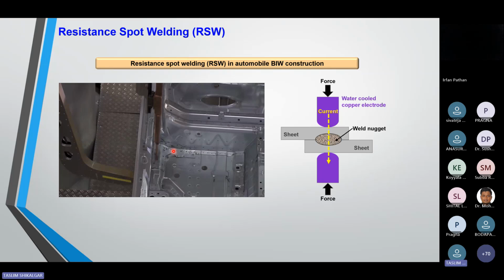connecting two sheets with the help of the resistance spot welding, and they are applying some force and passing some current. Now with the help of current they are generating this resistance spot weld, and here you can see this is the weld nugget, and people want to find out the exact mechanical as well as the fracture property of the nugget. So you cannot use the standard specimen to find out this property.